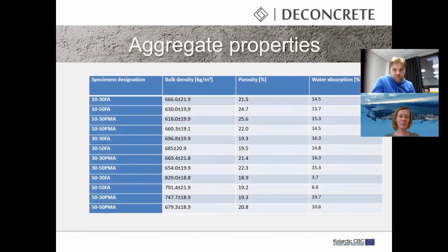And here are some properties like density, porosity and water absorption. I think that they were quite in accordance with the strength test results. And also these are again lightweight aggregates according to the bulk density. And I think that porosity and water absorption are as good or better compared to those commercial lightweight aggregates, which are the reference material.